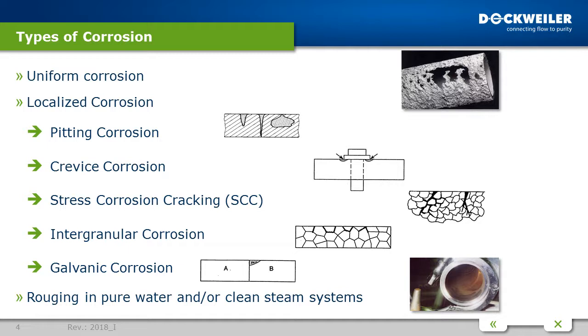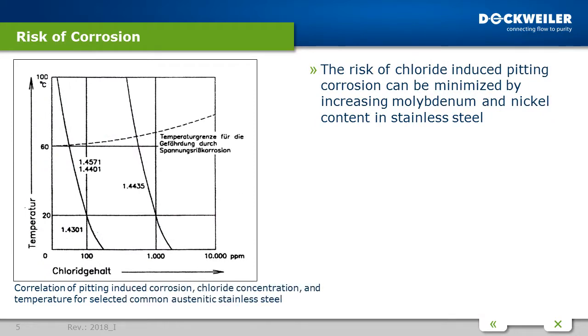Different media can cause different types of corrosion attack, and several forms of corrosion can occur in stainless steel. To understand how to prevent corrosion, one easy table shows the relationship between chloride content and temperature. The risk of chloride-induced pitting corrosion can be minimised by increasing the molybdenum and nickel content. For example, 1.4301 with added molybdenum becomes 1.4401, allowing higher chloride content and higher temperature before pitting starts. Increasing molybdenum and nickel further to the region of 1.4435 results in even higher temperature and chloride resistance.